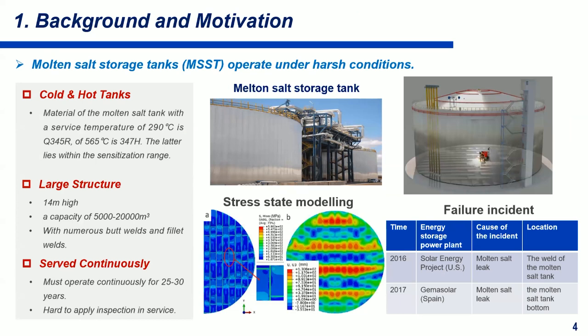Melting salt storage tanks operate under harsh conditions. The material of the melting salt tank with a lower temperature of 290 centigrade is Q345R. With a higher temperature of 565 centigrade, it is 347H. The latter lies within the sensitization range. It is a large structure with numerous complex welds and designed for 25 to 30 years. It is hard to apply inspection in service. So we will do research about in-service monitoring.